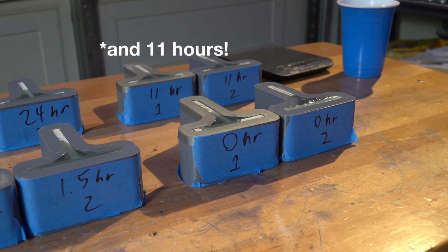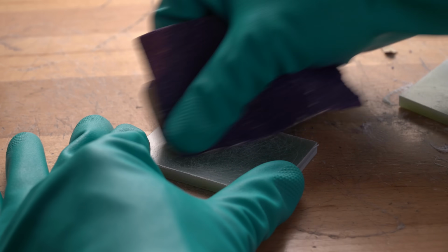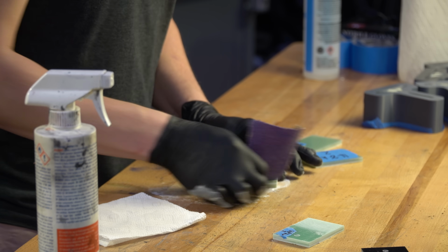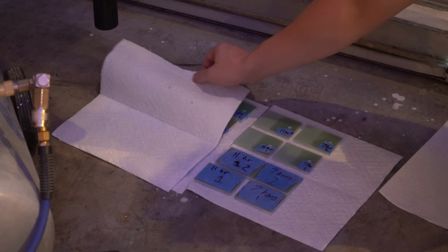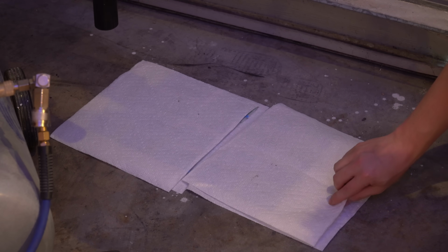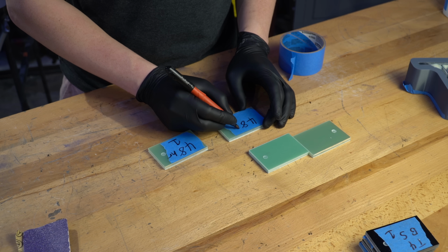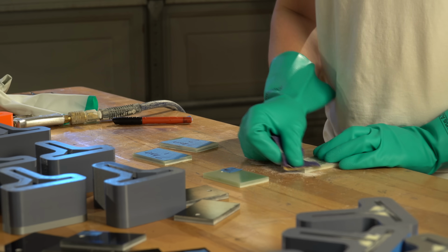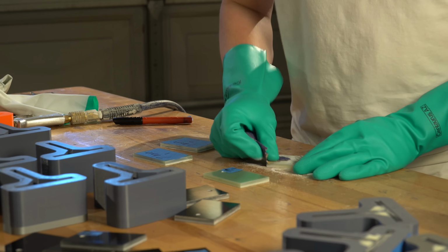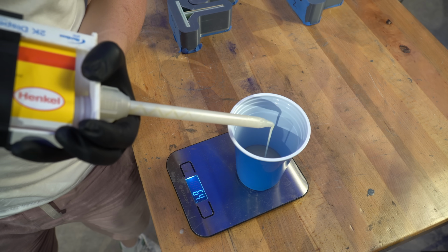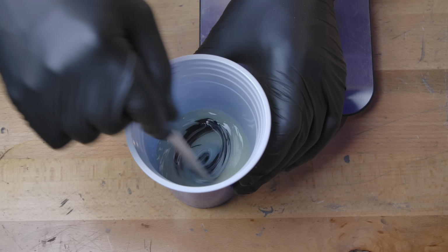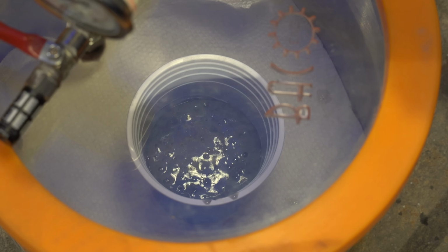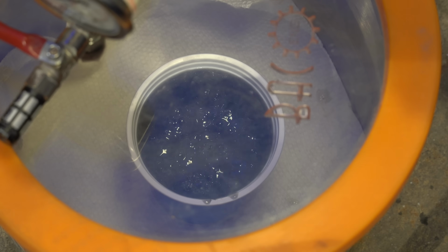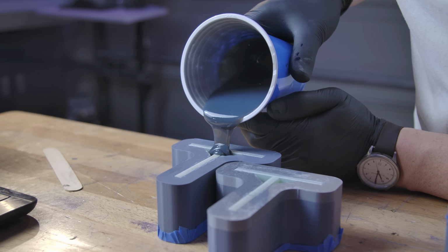Leading up to the bond, I prepped each sample at the right time so that I could glue them together all at once. After sanding each sample, I wiped it clean with isopropyl alcohol, then let it sit in the corner of my garage until it was time to bond. I didn't do anything else in the garage during testing, so the environment should be free of mold release, cutting fluid, machine oil, or other contaminants. I mixed the epoxy extra good in a cup beforehand with a drop of black dye, then vacuum degassed it in the cup. Then I poured that epoxy into each mold and vacuum degassed again to try and get the most consistent performance from each sample.